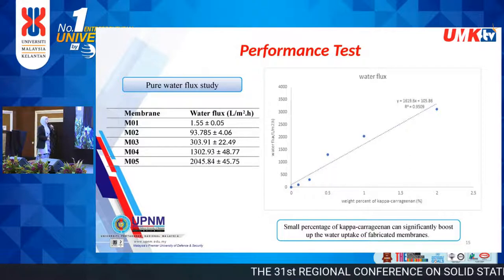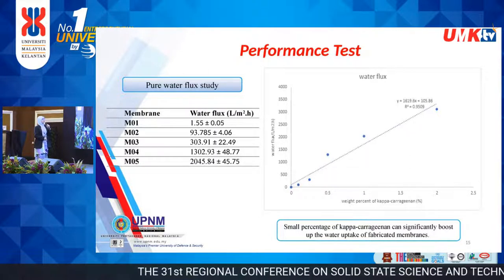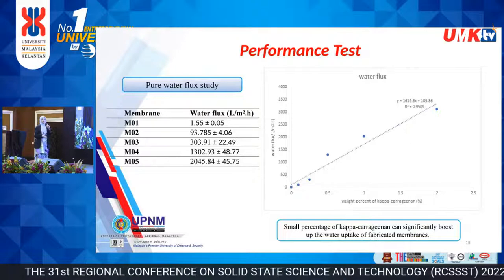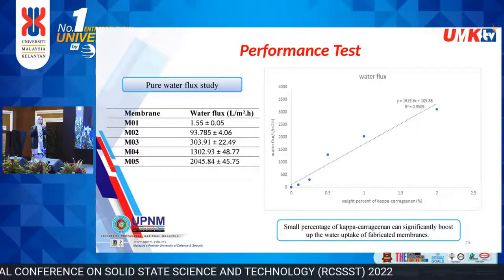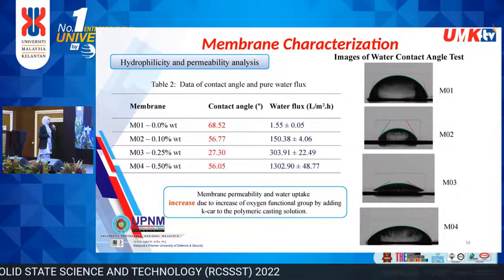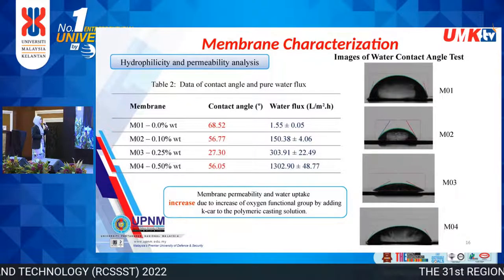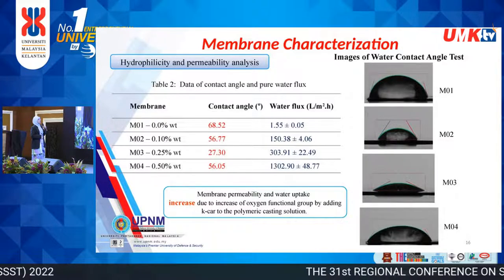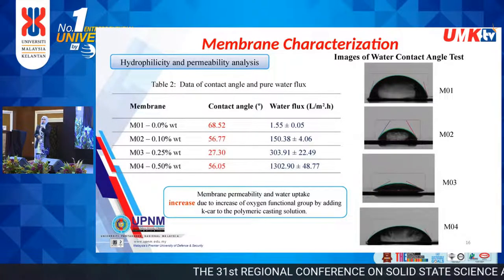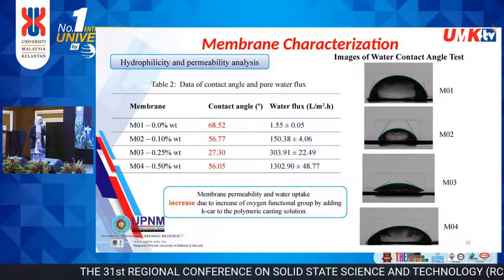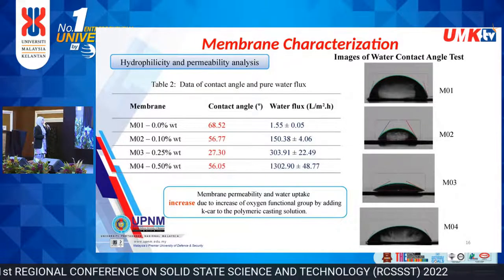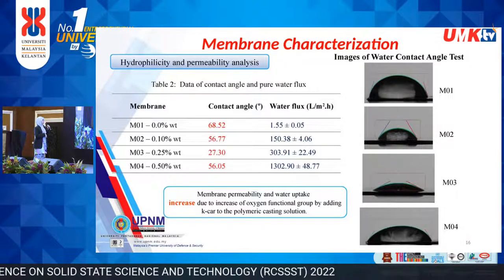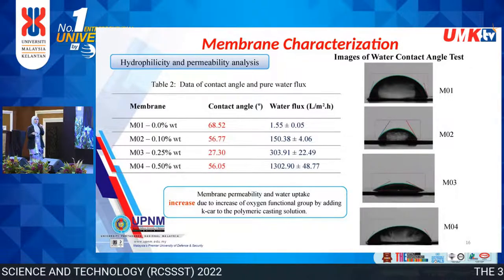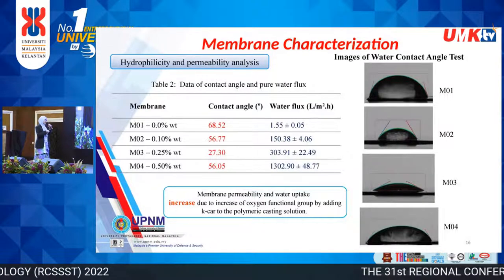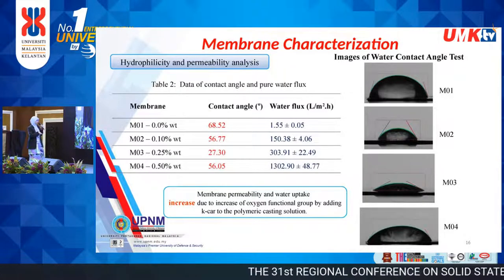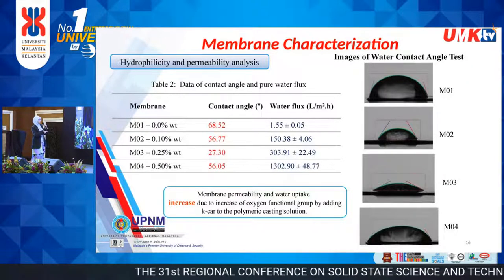Okay, so here are the results from a water contact angle test. This is to check the hydrophilicity and also for permeability analysis. What we can see here is that in comparison to the pure polysulfone membrane, the water contact angle is quite high, 68.5. By adding kappa carrageenan, it seems the hydrophilicity of the membrane is increased. But we are still investigating what happened with the membrane M04.